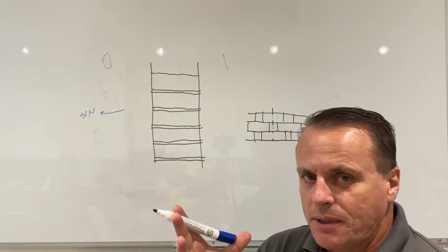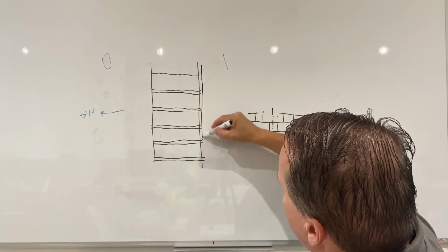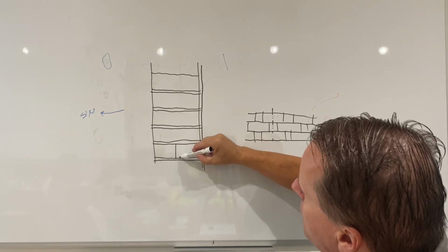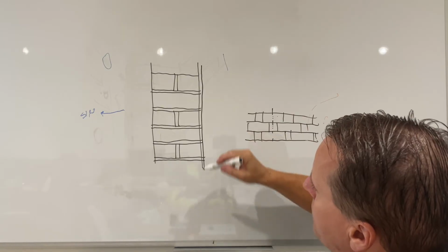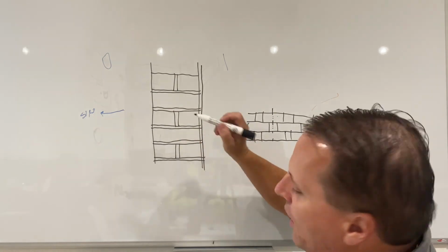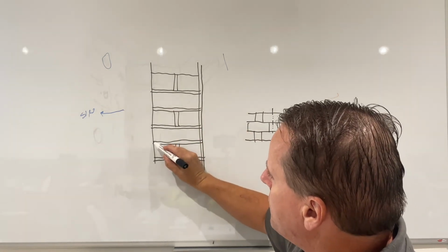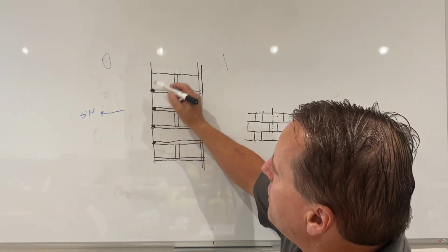So we then look into the property. We had a big area of blown plaster on one of the front walls. We can see there's a cement render put on the wall, which has blown, but behind that is a bitumen coating. So when this wall started out life, let's go back to my little sketch. When this wall started out life, 1800, whenever it was built, we've got our solid brick external wall, and we've got our lime mortar inside. Now, as we just said with that other example, over a period of time, these joints fail. What I suspect on this house from the general investigations that we did is that these would have been repointed using cement, as we said previously.